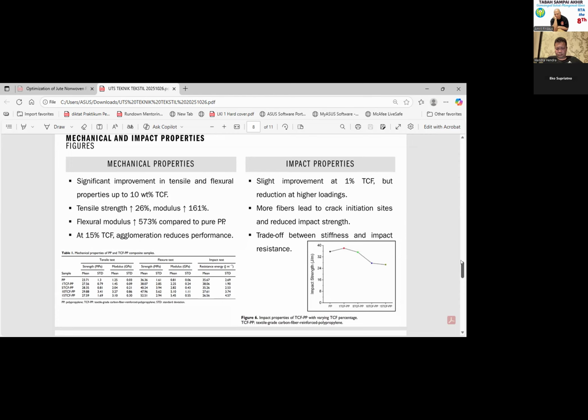But as the fiber content increased beyond that, especially at 10% and 15%, the impact resistance began to decrease. Why? Because the higher the fiber content, the more fiber ends there are within the matrix. These ends can act as crack initiation points, making the material more brittle or weak. In addition, when too many fibers are packed together, they can form regions that are stiffer than the surrounding polymer, and these areas tend to concentrate stress. So instead of spreading the impact evenly, the crack can propagate faster because of too many fibers in one location.